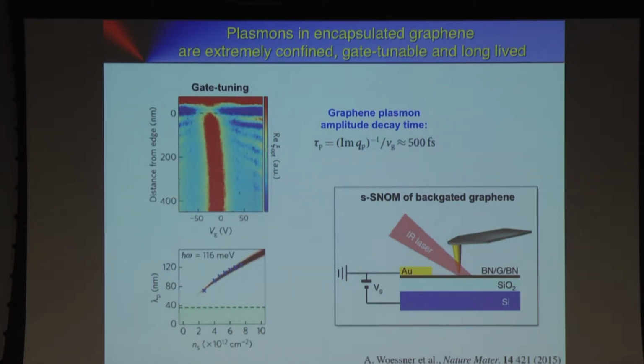And from this real space image, we can now measure the wavelengths of these plasmons as a function of the carrier concentration. And you can see that with a voltage in the range of a few tens of volts, we can change the wavelengths from about 70 nanometers to about 120 nanometers. So a quite large tuning range with a few tens of volts. That's the one thing. And the other thing is here we have 70 nanometers, and the imaging wavelength here again was 10 micrometers. So this shows electrical tunability of these waves plus a very strong confinement. And so this has a lot of potential to build optical circuitry. And SNOM is definitely a tool to study the basic properties such as wavelengths, how long these waves propagate, and so on.